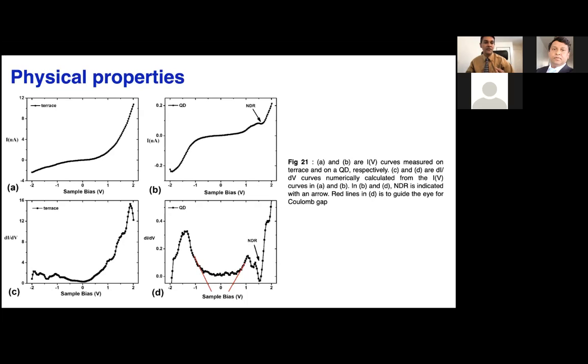Here you can see IV curves on both the terrace and the quantum dots. Around the Fermi level, you can see there's a non-zero conductance. Non-zero conductance is a well-known signature that the terrace and the quantum dots show metallic properties. Above the Fermi level, you can see there's a negative differential resistance. When we analyze dI/dV versus sample bias, figure D shows the suppressed conductance around the Fermi level. That is the signature of Coulomb blockade. So we measured this Coulomb gap. This resembles the opening of a band gap of a semiconductor around the Fermi level. It is a similar thing: it opens up a Coulomb gap. This Coulomb gap was around 0.7 volts.